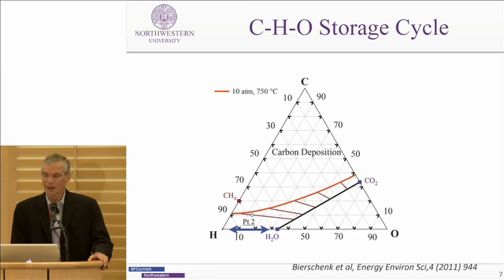What we're doing now is to add some carbon into the mix and going up, for example, to this point on the curve. Again, this line is basically going through the oxygen apex here, so you are basically keeping the same carbon-hydrogen ratio, but putting oxygen in or taking oxygen out as you do electrolysis or fuel cell operation. Okay? It turns out there's limits to where you can work, and it's basically in this region here, because this line represents fully oxidized steam and CO2, so you obviously can't go in here. And it turns out that if you become too carbon-rich, it becomes unstable to actually forming solid carbon, and you muck up your device with carbon, and you look very silly.